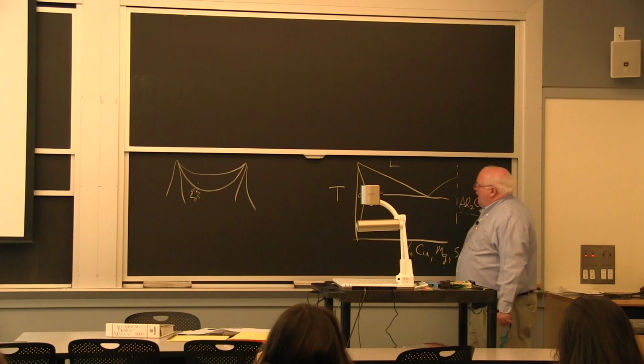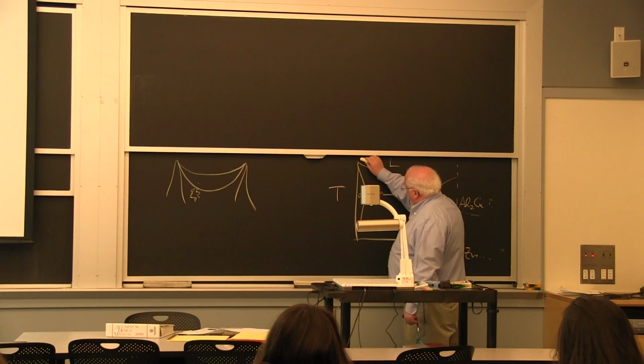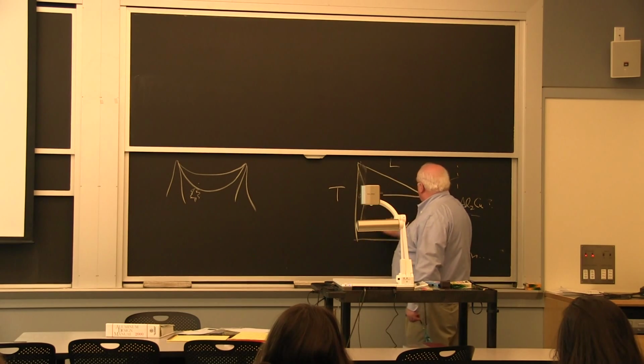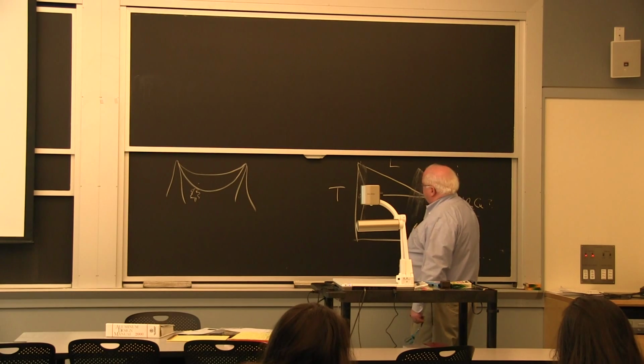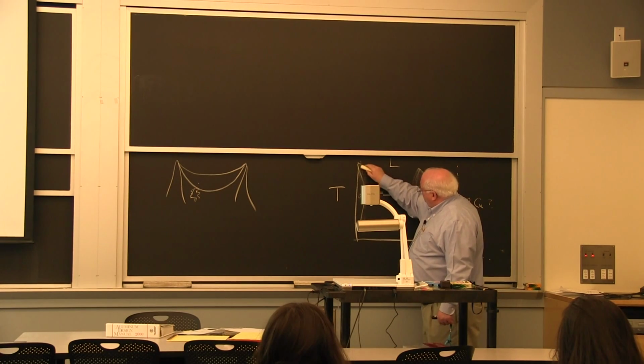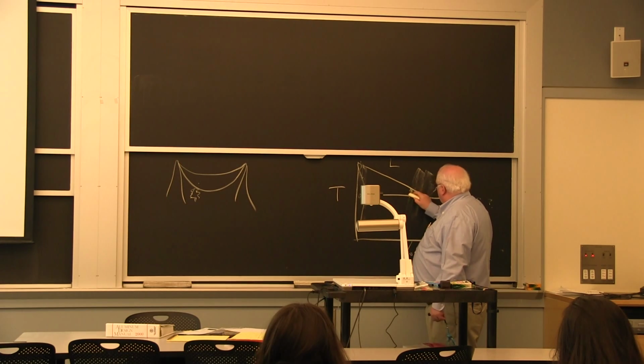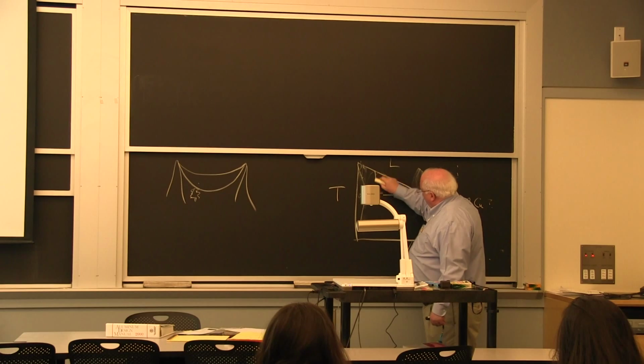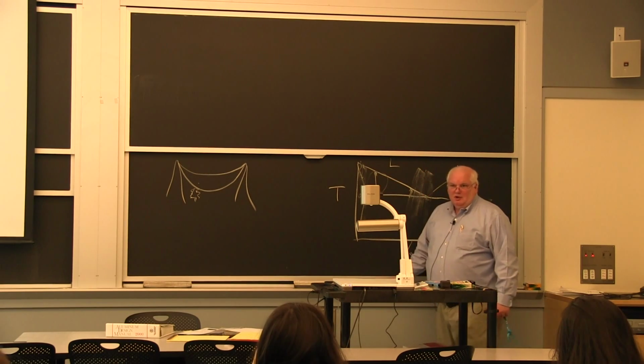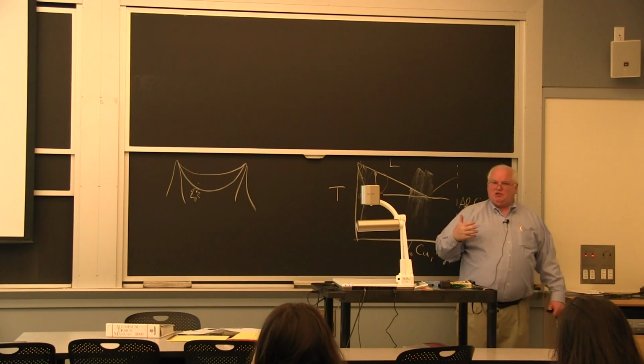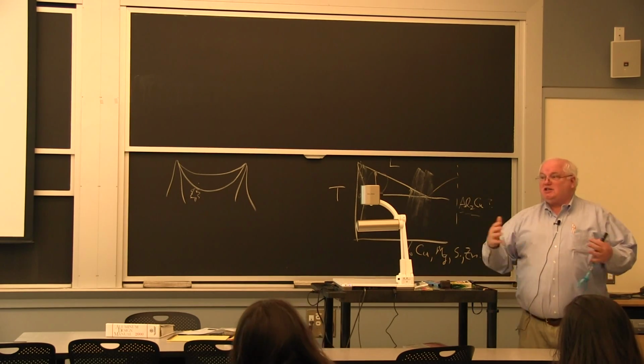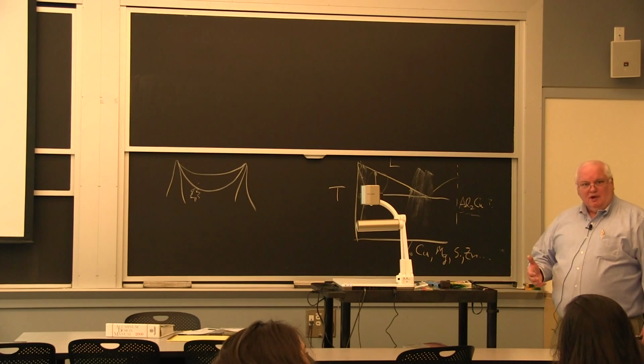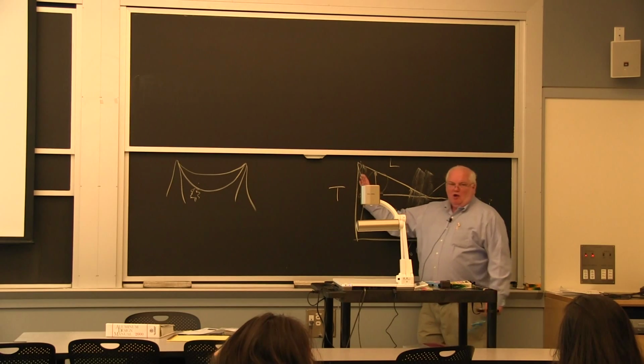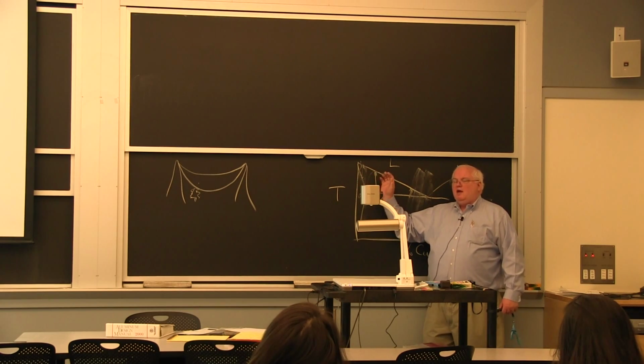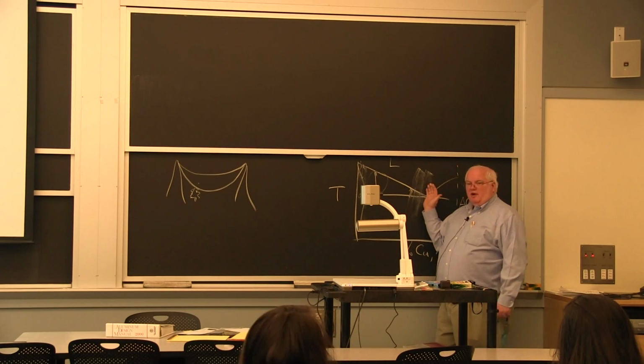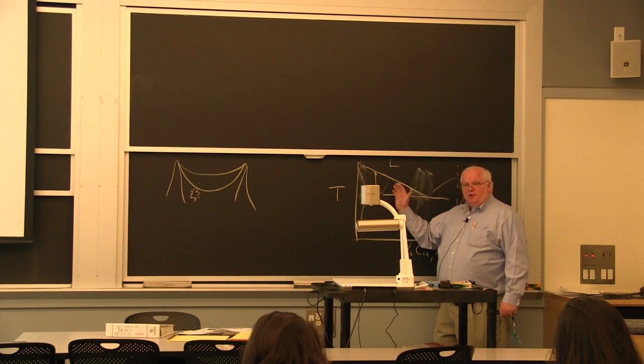that form. But basically for welding, we have 2 regimes. We have a regime right here, and we have a regime over here, where we have a relatively small freezing range. We don't like to work in here where the freezing range is large. Why? Because a big delta T in the mushy zone and a 6% volume shrinkage means lots of strain and lots of cracking. So you like to work with very highly alloyed aluminum, or relatively pure, lightly alloyed aluminum. You don't like the intermediate stuff in the middle.